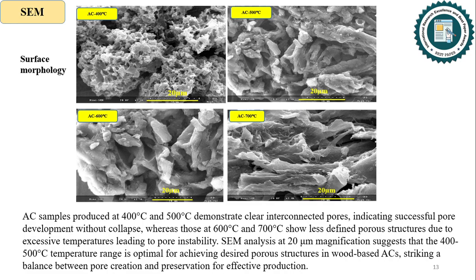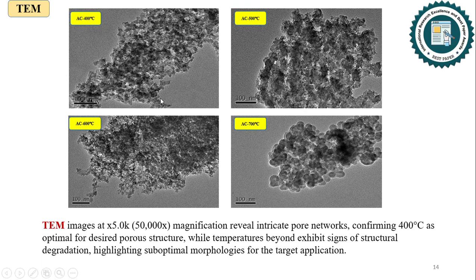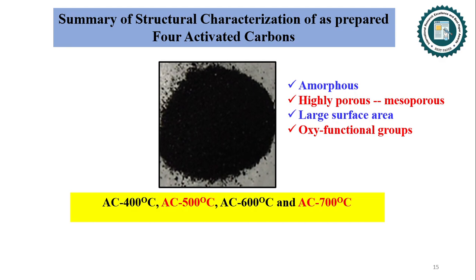effective production. TEM images reveal intricate pore networks, confirming 400 degrees centigrade as optimal for the desired porous structure, while temperatures beyond exhibit signs of structural degradation, highlighting suboptimal morphologies for target applications. It was seen that among the four activated carbons, the AC 400 degrees centigrade was found to be more amorphous in nature, highly porous with enormous mesoporosity, large surface area, and contained oxy-functional groups which are vital for supercapacitor performance.